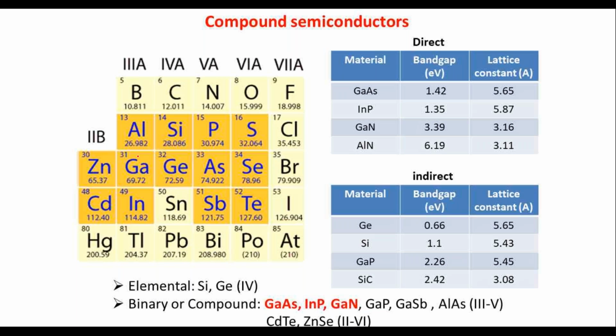In fact, you don't have much semiconductor or material choices. You can use only indium, gallium, aluminum, phosphorus, arsenic, and probably antimony. In fact, you have only 5 or 6 elements, and you will have to combine them judiciously so that it can support 1550 nanometer or 1300 nanometer.